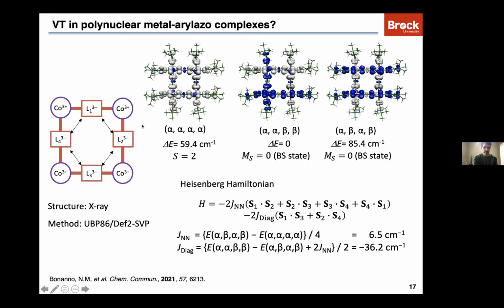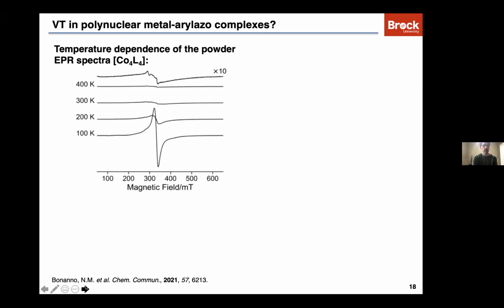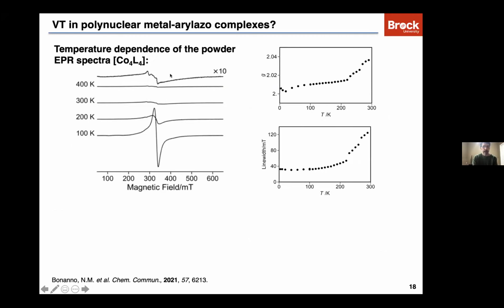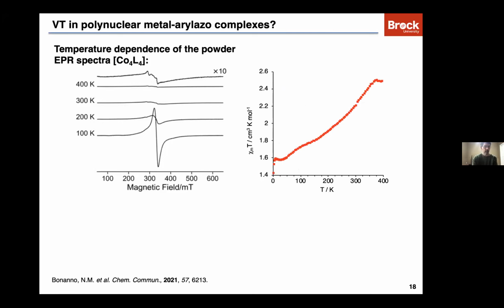Now, we carried out some powder EPR spectroscopy on this system. At low temperature, we see a typical kind of radical type spectrum that as we increase temperature changes, the lines broaden, g factor changes, all consistent with electron transfer. So as we increase temperature, what's happening is the ligand is reducing the metal. Okay, we have electron transfer from ligand to metal. In other words, valence tautomerism, and we even see that of course, in the magnetic data.